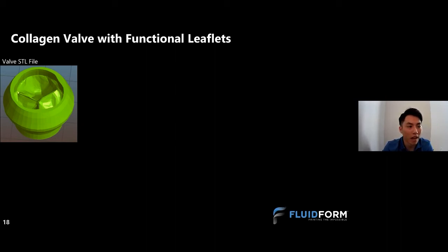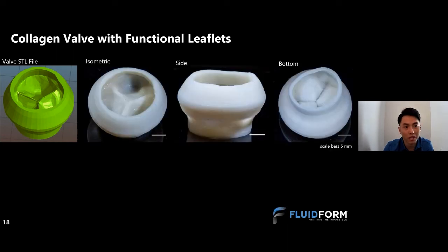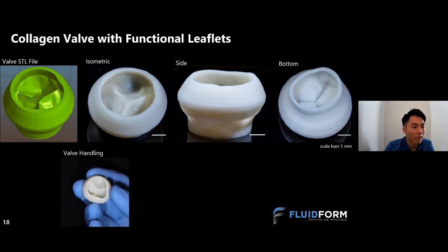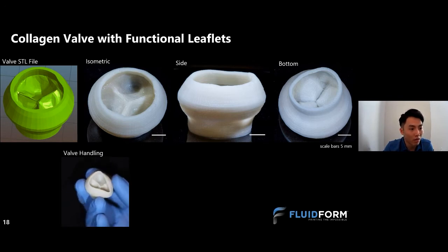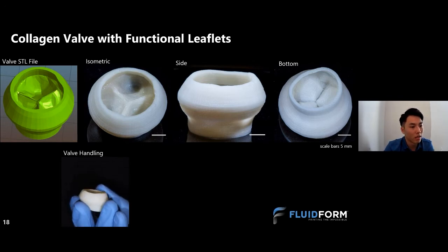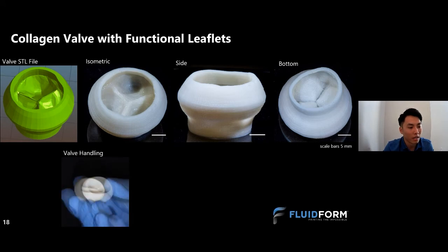Right, so we took a valve STL file and then we went ahead and printed it out of collagen 1 again. Shown here are different views of a printed heart valve in solution. And so here we show that the valve, when taken out, can actually be handled. The leaflets are patent, it's intact, and as a finger goes through and tries to manipulate some of these leaflets, you can see that the leaflets are manipulable.